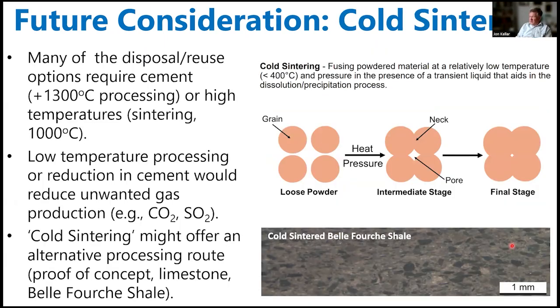Another consideration is so-called cold sintering. Over the last 15 years or so, there's been a lot of research done around this concept, primarily at Penn State, most notably. And the goal is really to reduce the sintering temperature. It isn't really cold. Usually it's less than 400 Celsius. The mechanism is different than the sintering that I talked about earlier. It's an incipient water that has to be present, but at those kind of intermediate temperatures, 300 Celsius, in the presence of water and pressure, you can actually get materials to sinter. And we've shown proof of concept with this around a limestone fine material and that shale. The nice thing is at those temperatures, you're not going to off-gas CO2 and SO2, and your energy costs may go down significantly in the process.